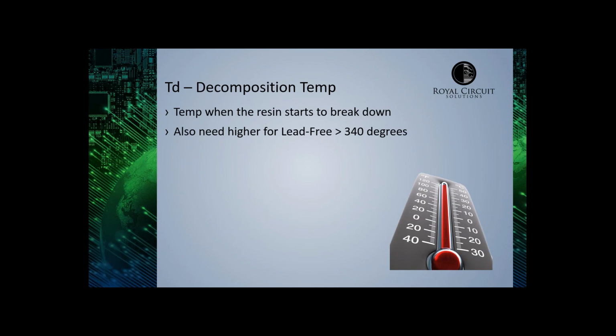Next property is the decomposition temp. This is when the resin actually starts to break down, burn up, or whatever it is. The decomposition temp is about when 5% of the resin is lost. So obviously, once again, you want much higher for lead-free applications, and it will also be much higher than T sub G. So for instance, for lead-free, when people talk about that, they want higher than 340 degrees. This is the point where you really want to avoid subjecting your board to. So you want to make sure that if you're dealing with some high temperature or some extreme environments, the decomposition temperature is much higher than what you're dealing with.